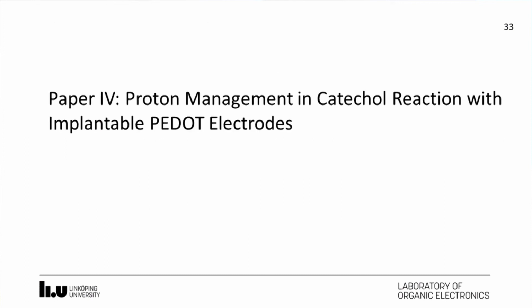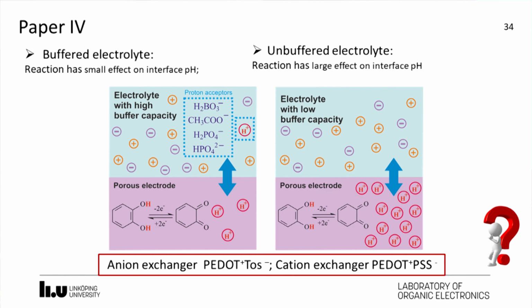In the last paper, we studied the proton management in catechol reactions with PEDOT polymers. As mentioned, catechol oxidation and the reduction of its corresponding quinones involves protons. So the release and the neutralization of protons will affect the actual pH at the interface. But in buffered electrolyte, because the buffer component can offset the actual pH change very quickly, the pH will change little, and in return, its effect on the redox chemistry of the catechol is very small. But in unbuffered electrolyte, the pH change will remain, and this remaining pH change will have a larger effect